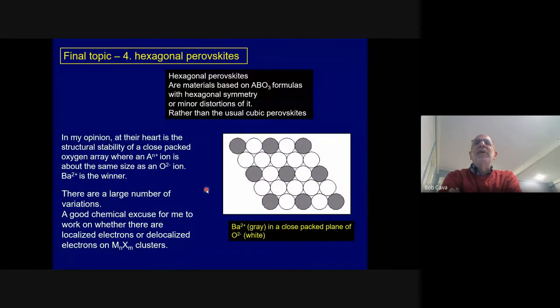And this is a set of materials that I realized was interesting for a bizarre reason. There are a lot of these things, and I don't hear people talking about this particular aspect of them much, which is that barium 2+, which is shown here in gray, is about the same size as an oxygen 2-. So we all learned early in our lives that closest packed lattices are very, very stable because the balls are all touching like this.